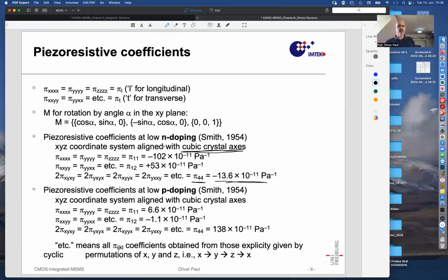That's for N doping. For P doping, the situation is different. Here, the longitudinal piezo coefficient along the cubic crystal axis is small. Yeah, minus 100 here is only 6. Pi 12 is even smaller, only 1 instead of 53. But to compensate for that, the shear piezo resistance coefficients, expressed as pi 44, are rather large. And etc. here means always that you can just replace the indices by cyclic permutation from replacing x by y, y by z, and then you get other combinations that are also equal. And those are the only coefficients that are different from 0.